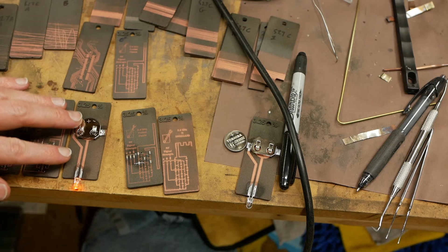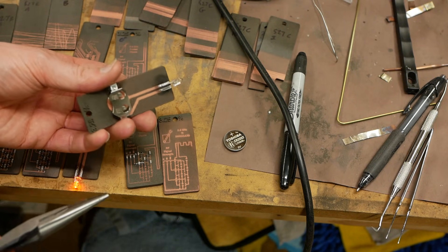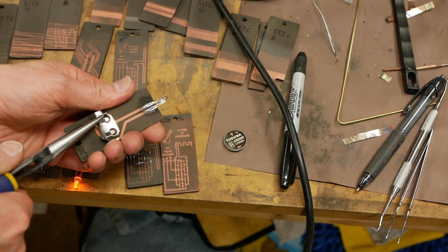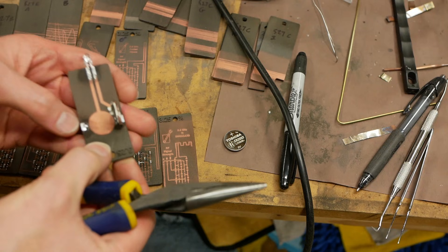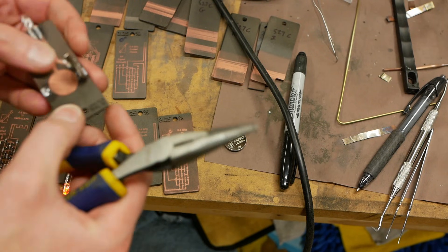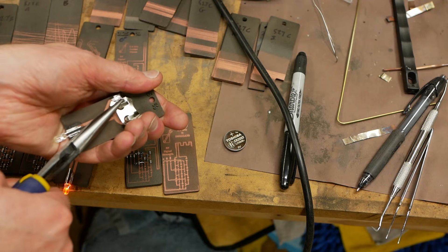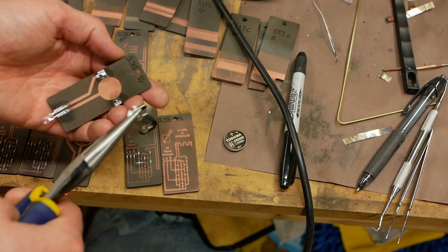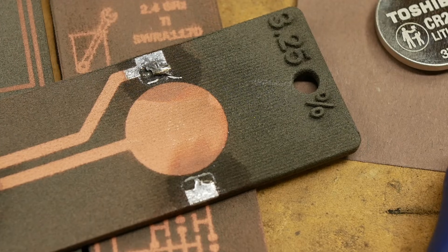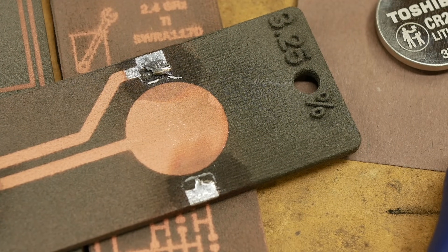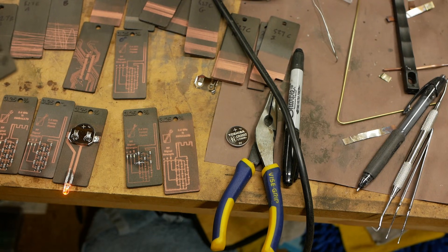Okay, let's rip one of these apart on camera. This is the first time I've actually destroyed one of these. So you can see my, hear my real reaction to see how good the adhesion is on one of these. Yeah, so that's about what I was expecting. In fact, wait a minute. No, no, it did actually pull the plastic out. I'll get some close-up shots of this. I mean, that's pretty good. I don't even think you would beat that with a fiberglass circuit board. In fact, yeah, that one actually ripped the metal even of the battery holder. So I think that, I think adhesion is pretty darn good, is my official rating.